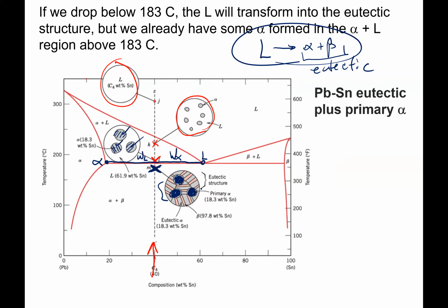All right, so this material now looks sort of interesting, because in this particular case I have alpha that's in spheres, and I have alpha that's in layers, just to separate out shapes. And then my beta, I only have in layers. I didn't form any beta before I got into the alpha beta region. So that's only in layers.